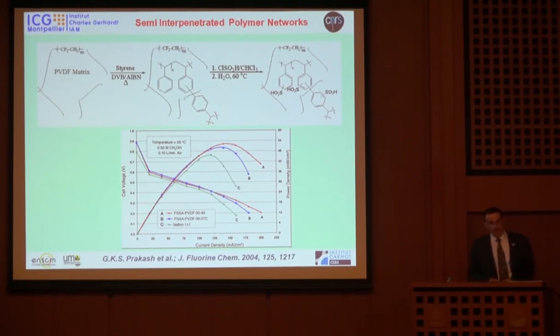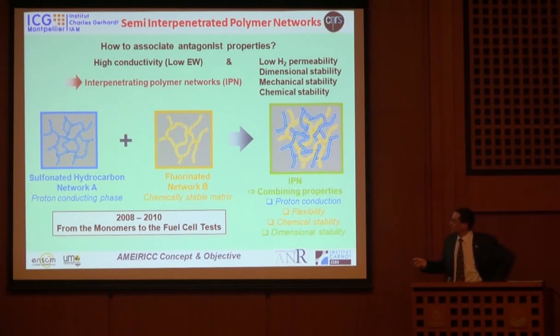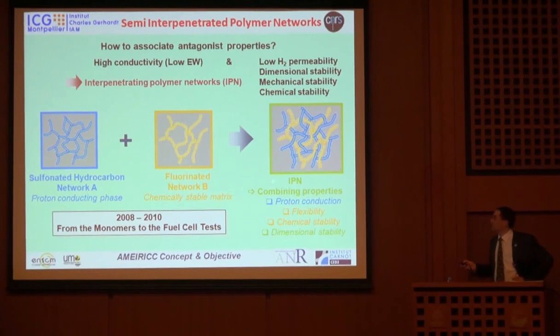So we tried to be inspired by this work, and it is very interesting to read literature. So I encourage the young PhD students to read. This is very important, to read literature. And we said it should be interesting to also design an IPN with a fluorinated polymer, and another polymer which brings the sulfonic acid group. And this is exactly what we tried to design. We tried to do a network with some colleagues in Lyon, with a polymeric counterpart coming from diacrylate, and here to have an IPN, so an interpenetrating polymer network, because in this case we need high conductivity brought by the sulfonic hydrocarbon polymer, and we also need low hydrogen permeability, good dimensional stability, good mechanical properties, good chemical stability brought by the fluorinated counterpart.